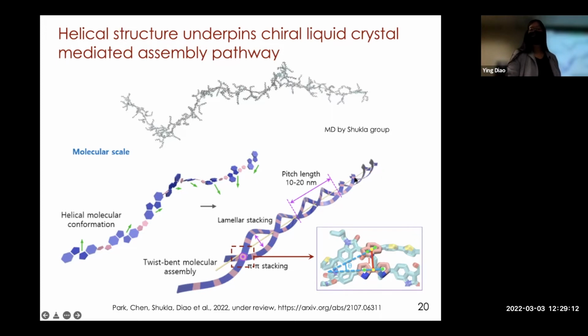Having imaged this structure and validated it by electron microscopy, it really changed how we think about the structure of these polymers. Usually people think of them as layered structures driven by pi-pi stacking, but they can assemble into helices. As we'll show, this can radically change the electronic properties.